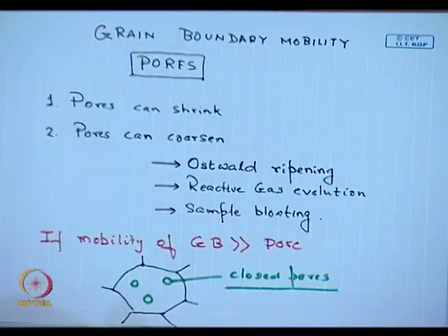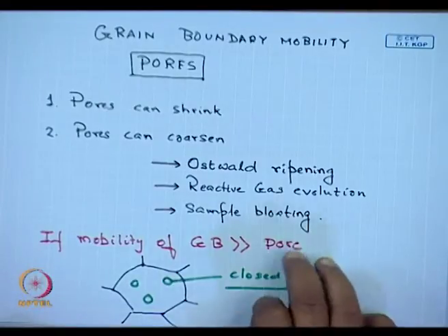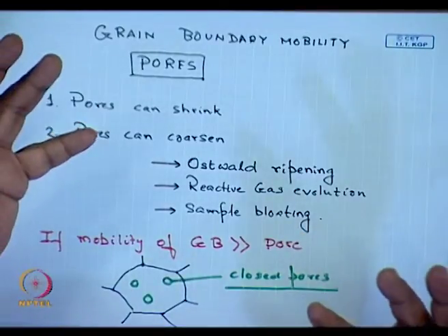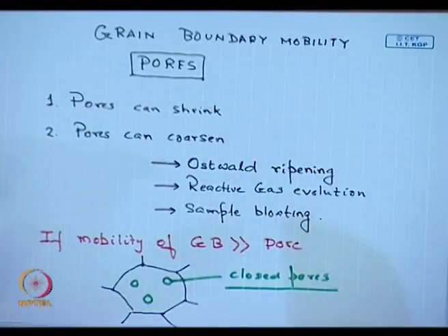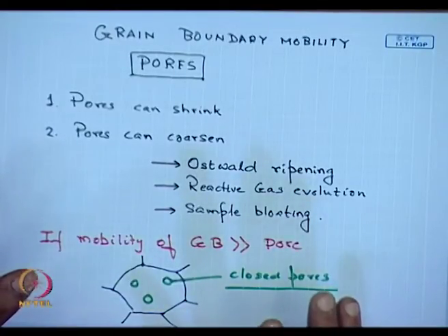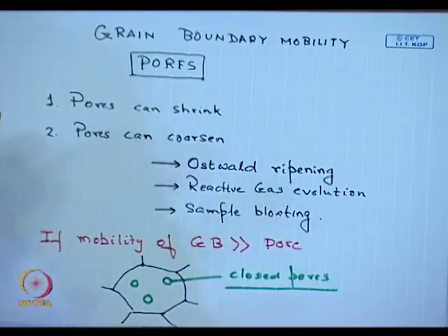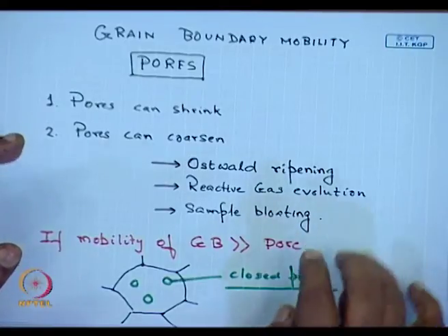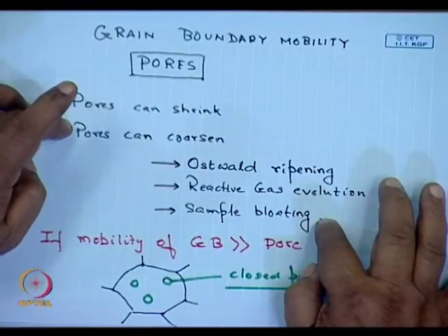Sample bloating, this is a major problem. There are many clays which swell up when they are heated. It is true that today we have learned how to make use of that bloating to increase the engineering properties. But sample bloating also can happen, which can lead to coarsening of pores.